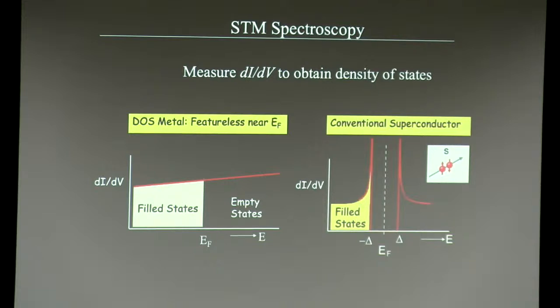If you measure the di/dV for a superconductor, you should see no states at the Fermi energy, because we are tunneling in single electrons and all the electrons in the system are paired. So the density of states up to the gap energy will be zero, and then right at the gap energy you see these strong coherence peaks.